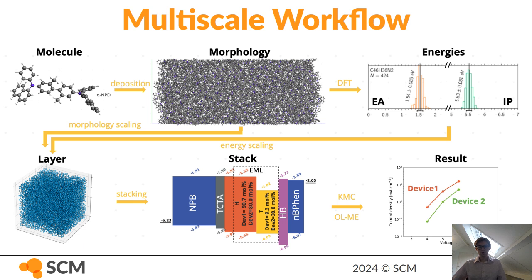These properties that we obtain from the morphology are then used to represent the different layers in our OLED stack, which we can then go and study using mesoscale techniques such as KMC to obtain an idea of what the process characteristics are like at longer time and length scales. It allows us to include long-range effects, long-range electrostatics, the role of the interfaces, and this is all information that we can then use to determine parameters of the actual device, focusing on the efficiencies and the overall emission spectrum, and we also take into account optical losses.